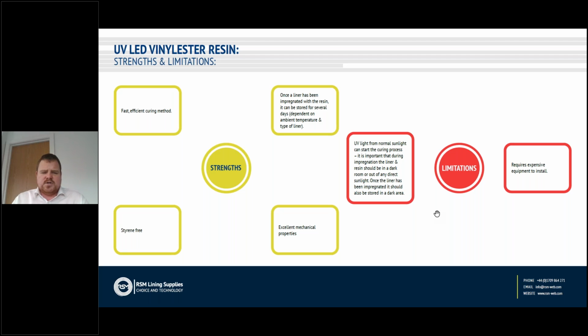In terms of the limitations of this method, we must be incredibly careful as to how we handle the impregnated liner. The resin is sensitive to UV and LED, so it really must be kept out of direct sunlight during installation, if at all possible. And the newer technology is a little bit more expensive than our traditional ambient heat and steam cured systems. However, with that you get a greater degree of speed and also a greater degree of knowledge about the curing process.